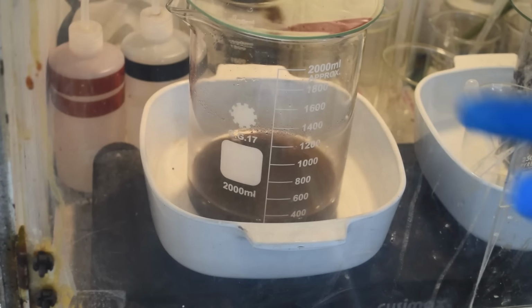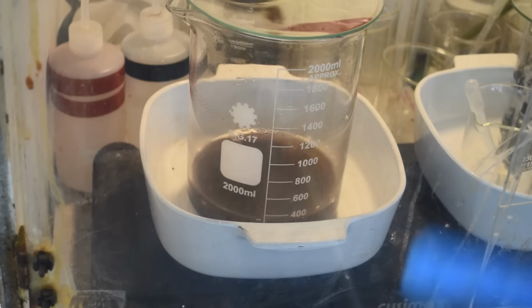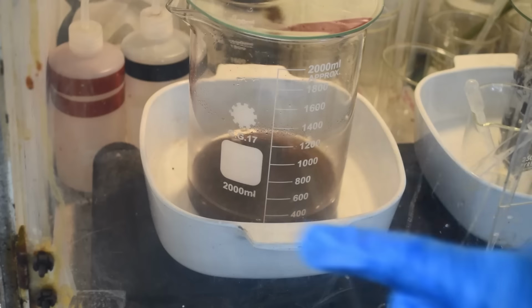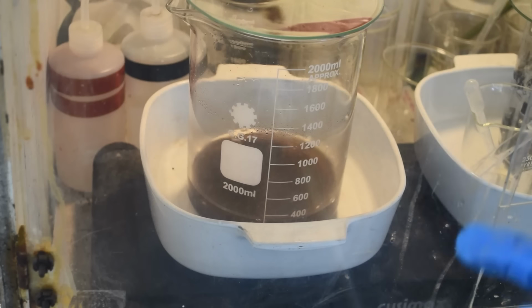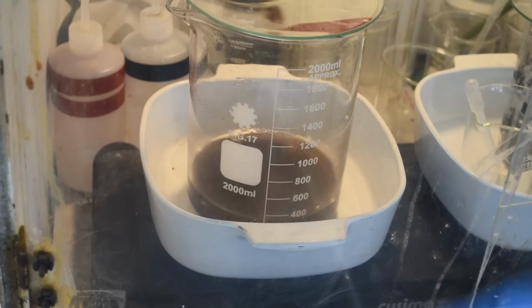All right, there we are in the fume hood. I've got a couple hundred milliliters of distilled water on it, and I've turned the heat up on the hot plate. We'll bring this up to a boil. I like to boil it in distilled water first, before going to any hydrochloric acid boils, just in case there's any lingering nitrate in there. I don't want any of the gold going back into solution. So we'll boil it in distilled water first,